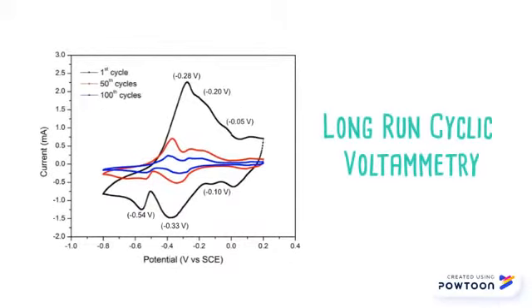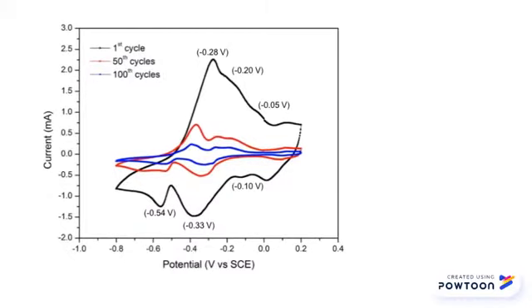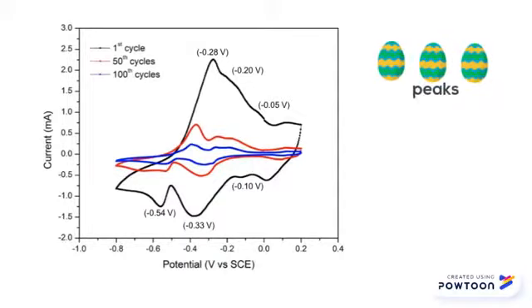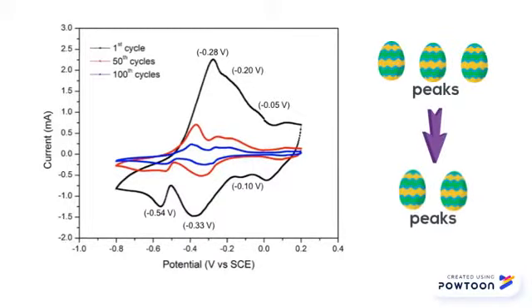Besides, long-term CV can be used to determine the stability and degradation behavior of the anode influenced by the binder. The CV curve decreased upon cycling and the redox peaks decreased from 3 peaks to 2 peaks. This might be because of the loss of Li ion for the reactions, resulting in no phase transformation at the third redox peak after 100 cycles.